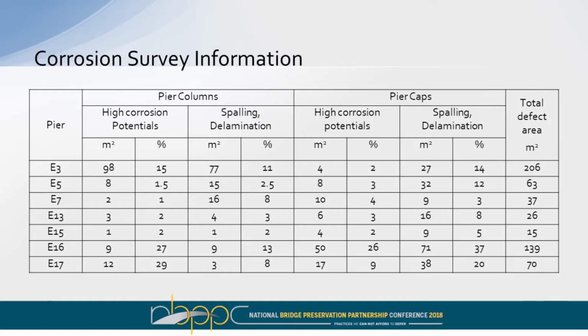This is a project in Ontario where they did a corrosion investigation. You saw, not everything's corroding in a similar way. You had some areas that had more contamination, higher corrosion potentials, and some variation there. So the DOT basically came out with a system where, in some cases it was just lower levels of damage, they did concrete repairs, and in areas with lower levels of damage but higher corrosion potentials, they did passive cathodic protection, and that was with the metallizing system.